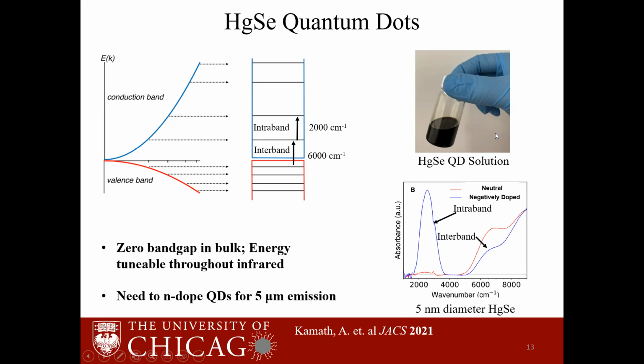nanometers. And one important point I want to mention here, since usually in semiconductors, the valence band is full and the conduction band is empty, we do not observe intraband transitions. So in order for us to see these intraband transitions, we need to find a way to put electrons into the conduction band. So we need to negatively dope the quantum dots. And so now that we have the core material, our next step is to decide what is the material for